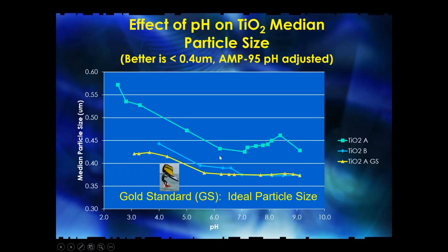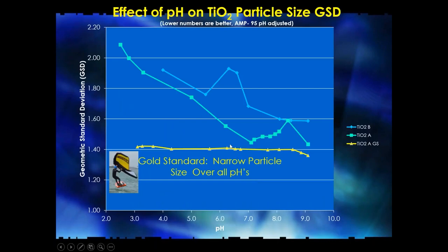So we took another commercial product and we checked its particle size distribution, and it didn't matter whether you had the co-dispersant or not. Now, how am I getting these GSDs? Again, we go to the Horiba. Remember those curves that showed how they were growing and expanding? It's the width of the curve that kills you, okay? The average particle size looks pretty good. And it really didn't matter whether you used a co-dispersant or not until you go to look at the GSD. Now, this product from company A, which was not modified in any way, has pretty good GSD.